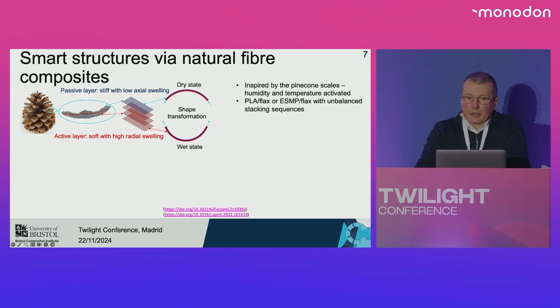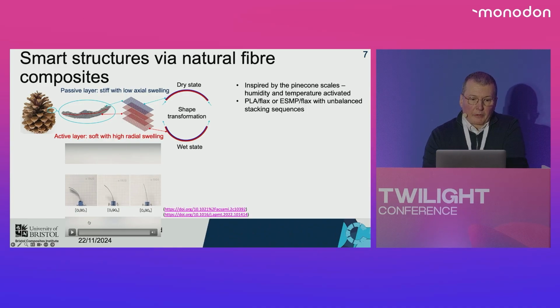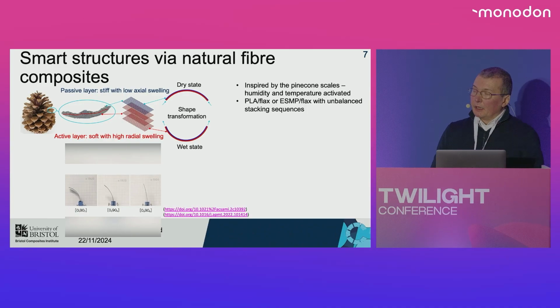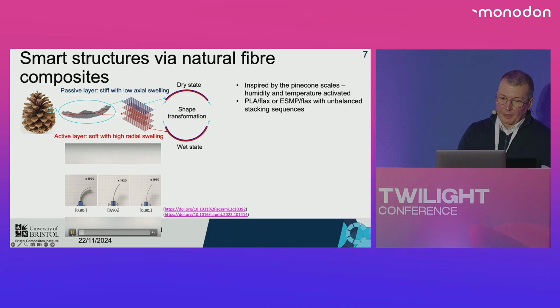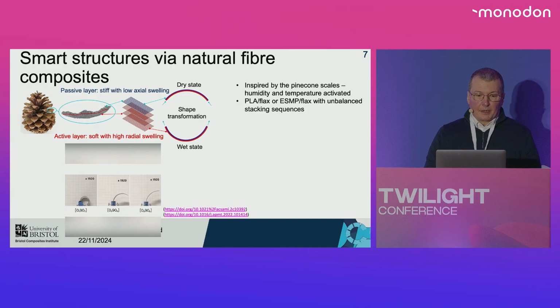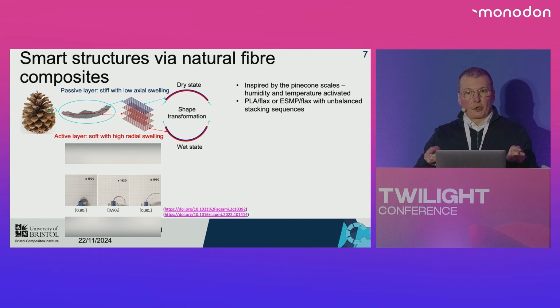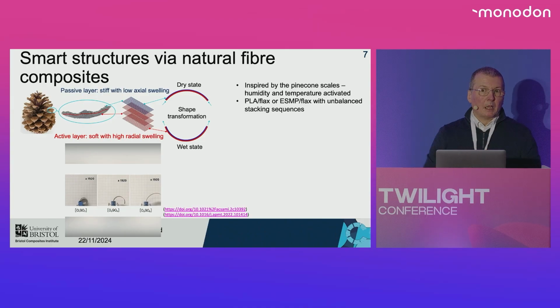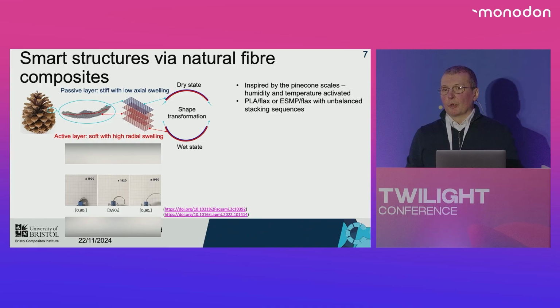And inspired by pine cone scales, we have developed several classes of thermoplastic composite with PLA, but also shape memory epoxy flax composite with this kind of unbalanced stacking sequences. Just to give an idea what happens when you use this type of architecture with these epoxy flax fiber composites, and when you have changes in humidity, you can see in these quickly accelerated videos, the actuators have this type of in-plane coupling between axial and transverse deformation. They provide this kind of out-of-plane change of curvature when there are changes of the relative humidity, or when you take the actuators and you chuck them in water.